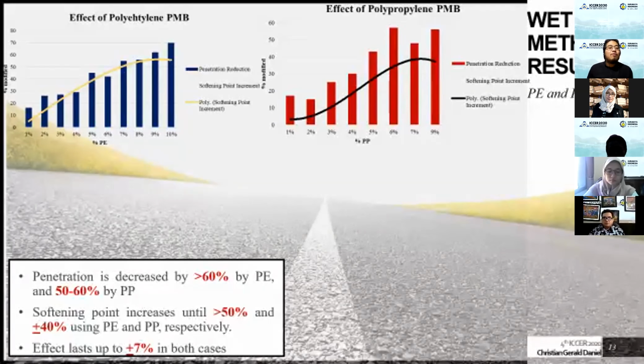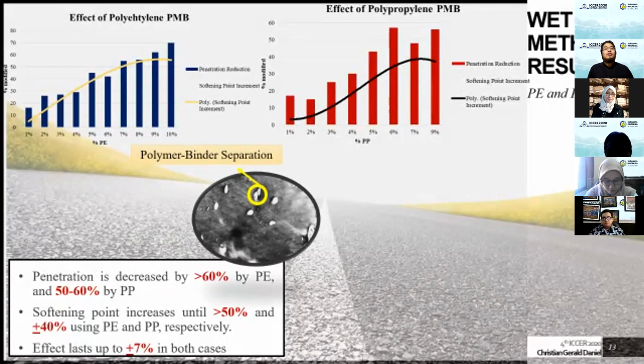And the effect of both modifications lasts up to only around 7% in both cases, beyond which the effect starts to deteriorate. You cannot really see the improvement anymore. And one thing to be taken into account, we have a phenomenon like this, polymer binder separation. The highlighted one is the polymer. It cannot disperse entirely inside our binder or bitumen because of the differences in density, and they don't have a really strong chemical bonding. So that's why this could happen.